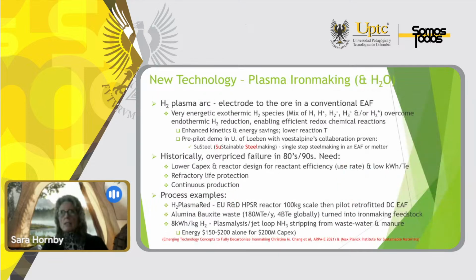Plasma iron making is starting to raise its head again. This was around the late 80s, early 90s, and basically failed because it was overpriced back then. It does have the advantage of producing very energetic exothermic hydrogen species, which overcome the endothermic nature of hydrogen, which is an issue in some processes, and it enables efficient redox chemical reactions. It has enhanced kinetics and energy savings potentially and lower reaction temperature.